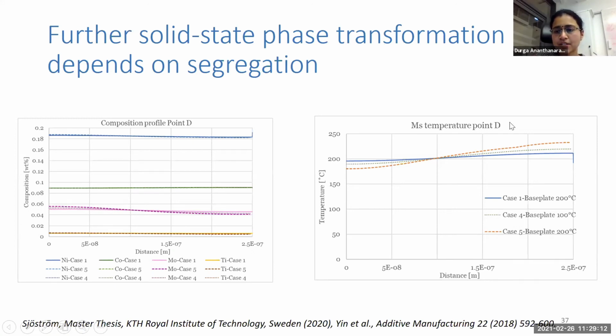She also did this simulation for different cases, varying the base plate temperature. If you have a base plate that's above the martensite start temperature, then in that region you would not have martensite transformation happening. This is similar to what we see in the experiments, because in the interdendritic region the austenite is still retained in many places. So we are able to correlate what we observe in the experiments with simulations like this. As I said, it's not sufficient to just use alloy composition and calculate the martensite start temperature. The effect of segregation is important in cases like this for predicting solid state phase transformation.